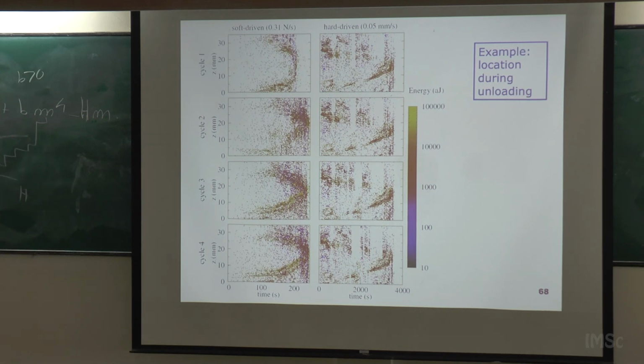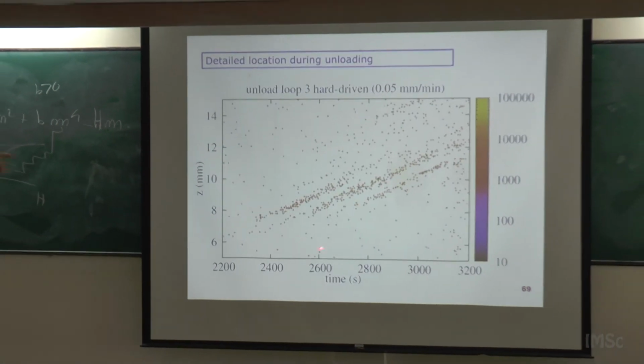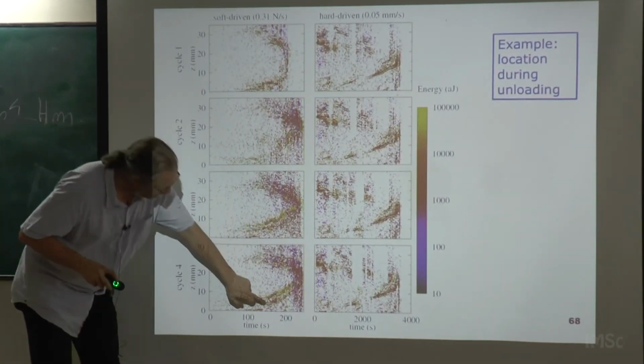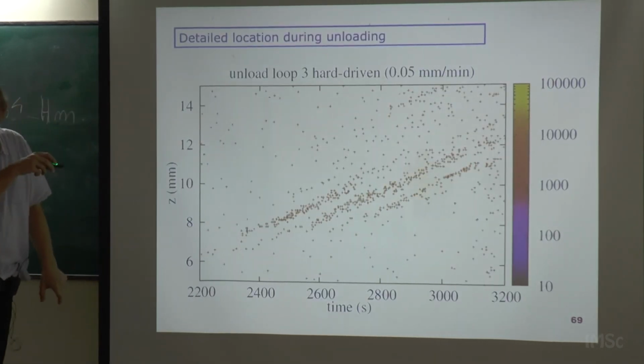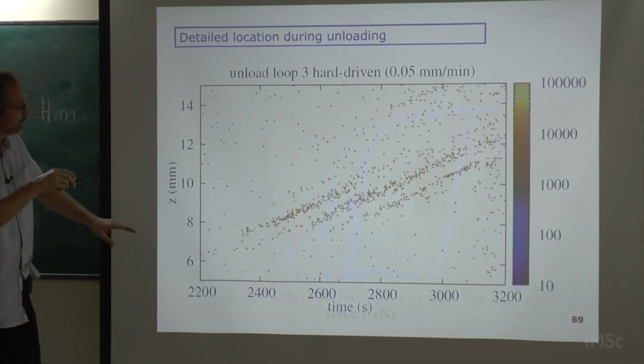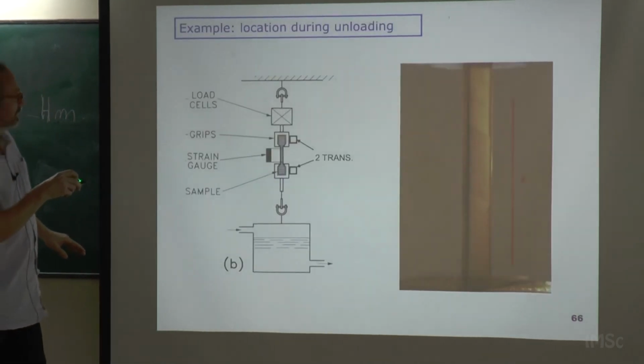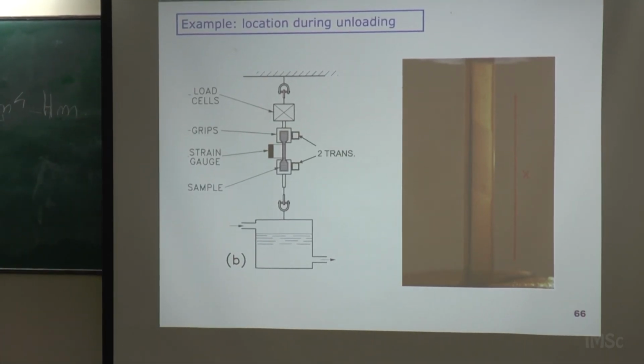So if you plot the distance between two successive avalanches, does it show some? We haven't, in this context, analyzed that. We did this kind of analysis for the porous materials, and there we have a force, one of these analyses, correlating the avalanches with the force drop. But here we haven't. Okay, but what is nice is that, for instance, here, when magnifying this part, you can discover this kind of lines, and this is because the transition, well, let me show. The transition is advancing like that.